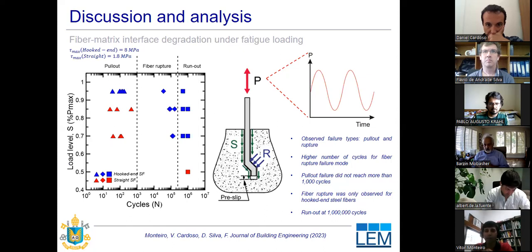For the fiber rupture, we need more cycles for it to happen, and it is majorly controlled by the fracture or the degradation of the steel wire inside the matrix. So one is controlled by the interface degradation inside the matrix, and the second one is controlled by the degradation of the steel wire, which also degrades during the fatigue. The steel material degrades along the test.